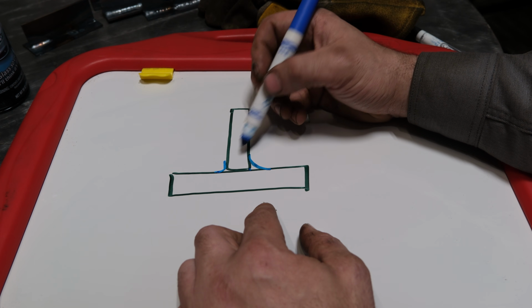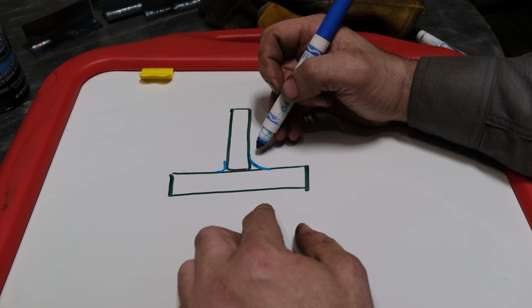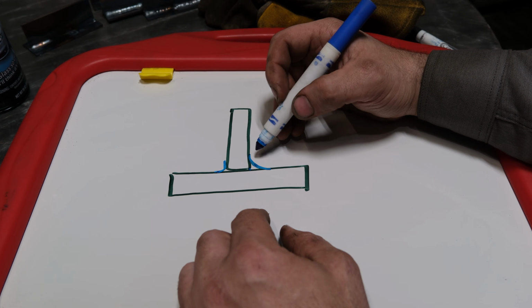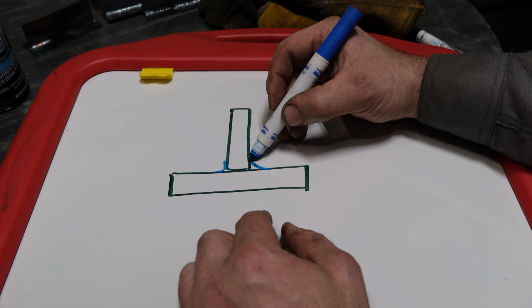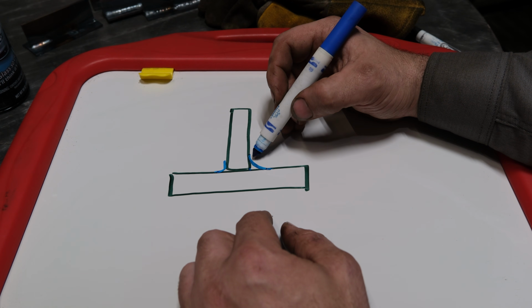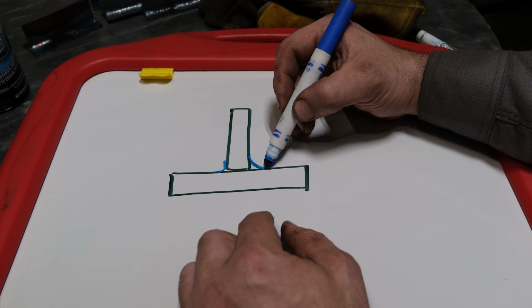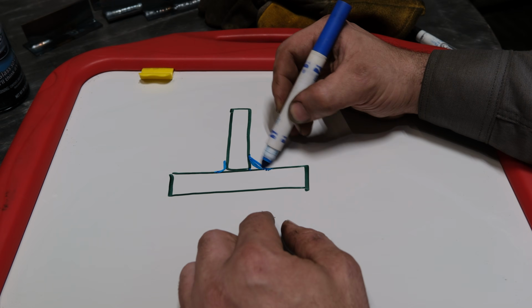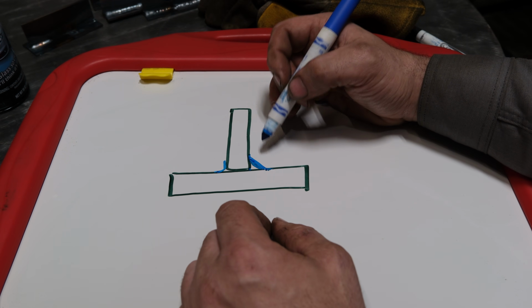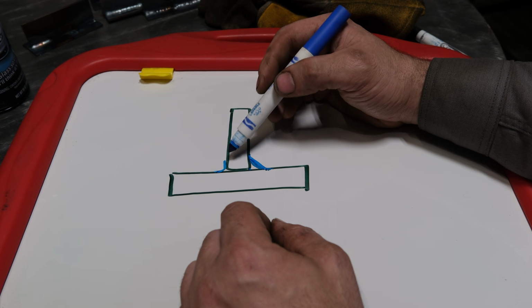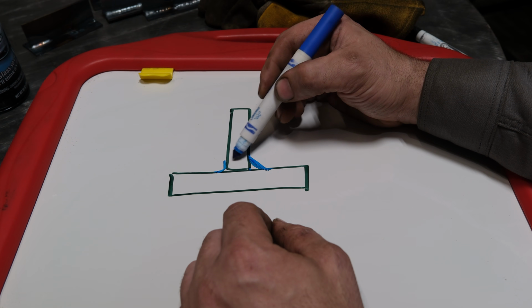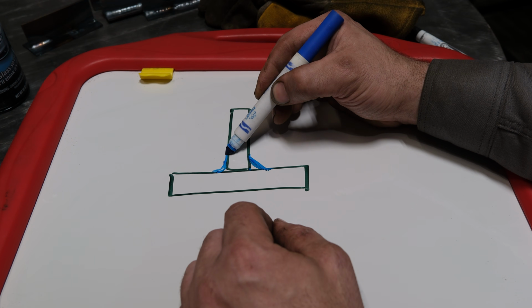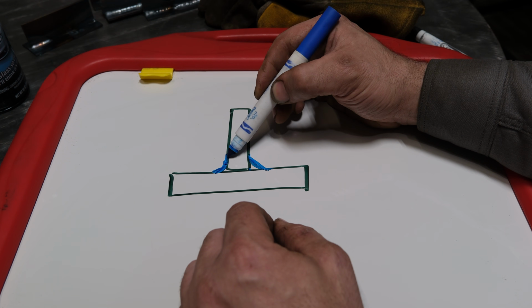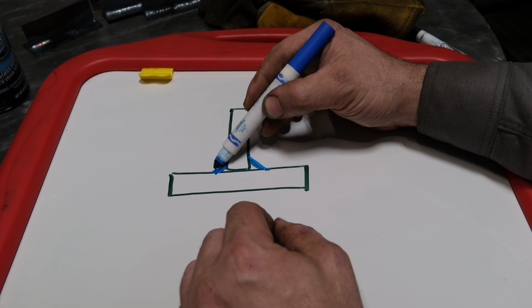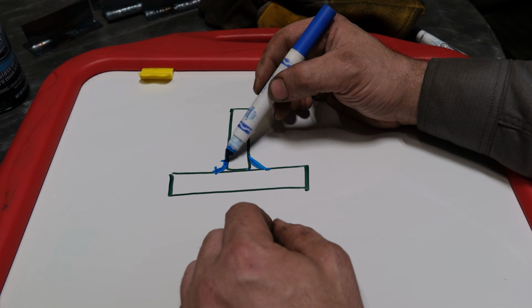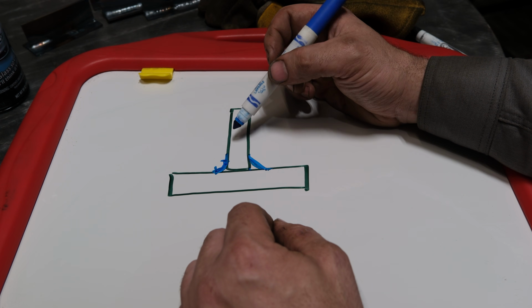There will be no reinforcement, minimal fusion, and you get the picture on that. Now, TIG welding in general, because of how the arc works, generally will have a concave profile. It is very difficult to produce more or less a flat bead like this, like you would see with maybe spray arc or dual shield. However, you need to push enough filler to where you don't have something that looks like this. You would want something more like this, and not this far up. So again, somewhere right here. So very small, but a little bit convex is okay.